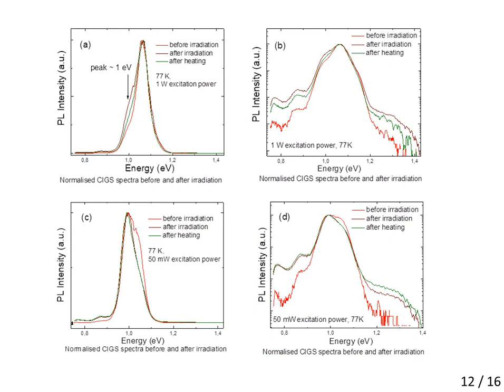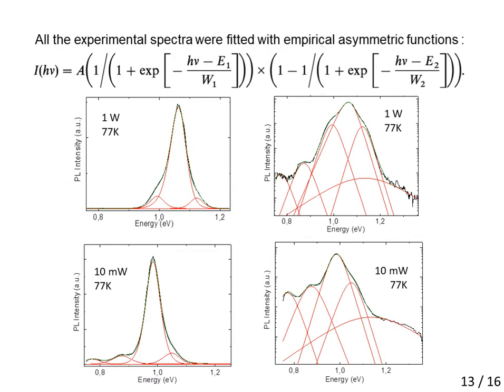Normalized spectra before and after irradiation are shown on this slide. To evaluate the changes, all photoluminescence spectra were divided into separate bands. Such decomposition allows not only subtracting one band from another, but also estimating their shape. The shape of the photoluminescence band associated with the valence band tail can be accurately fitted with a double sigmoidal function. The dominant band that we see at maximum excitation power almost disappears at 10 milliwatts.